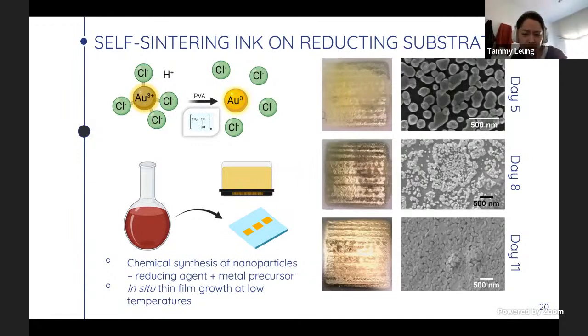So the reducing mechanism that we were discussing previously was based on the use of plasma conversion. However, we discovered an alternative process that produces an equally conductive film at room temperature. Here, the reducing agent is the substrate itself, which must contain numerous hydroxyl groups in order to initiate the reaction. In this case, we used PVA, which was able to form a conductive film within 11 days at room temperature, without needing any external sintering technique. For a more instantaneous result, the sintering temperature can be increased and forms a similar layer within 30 minutes.